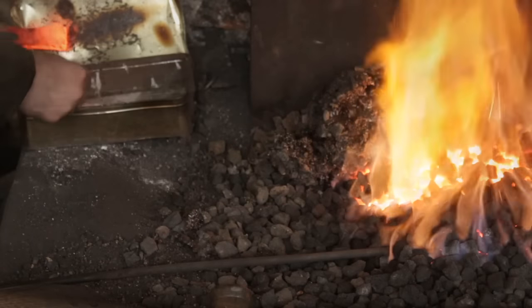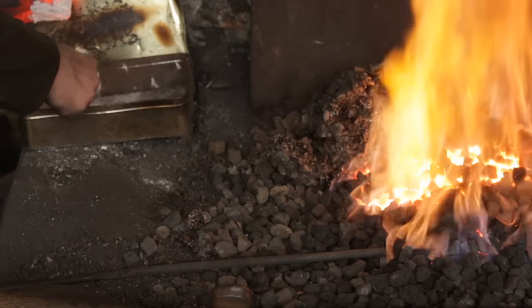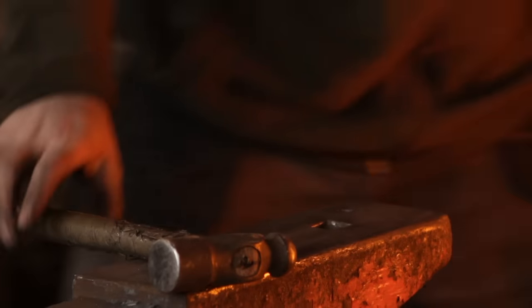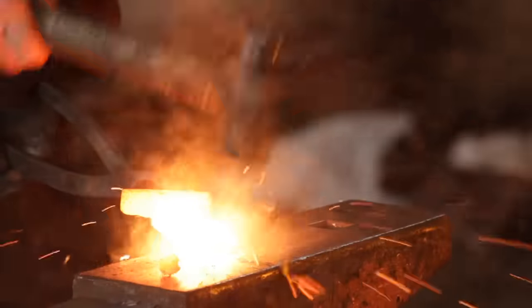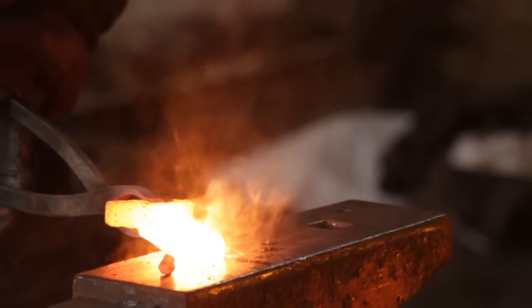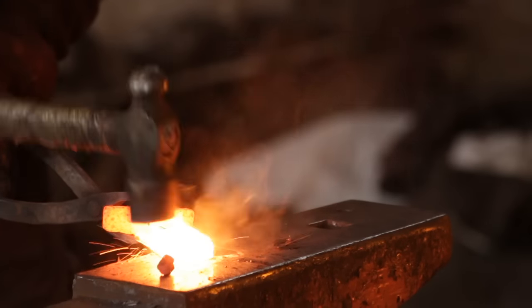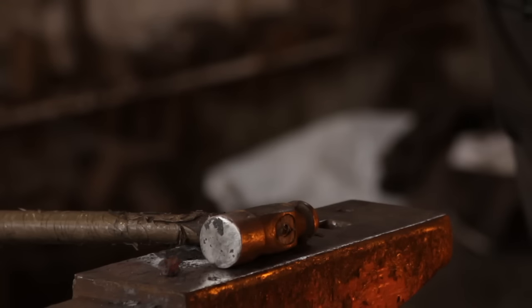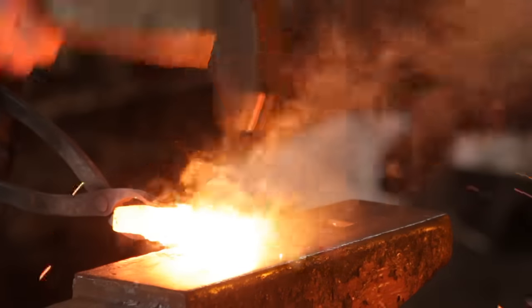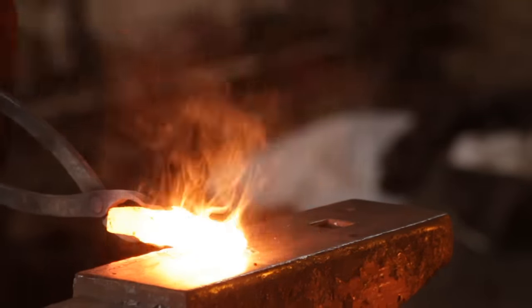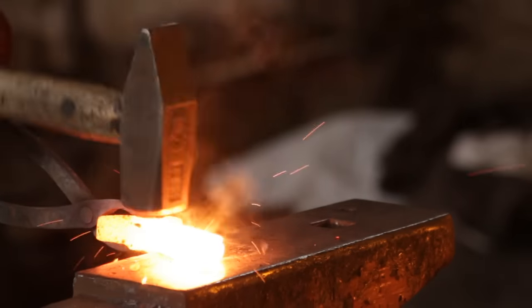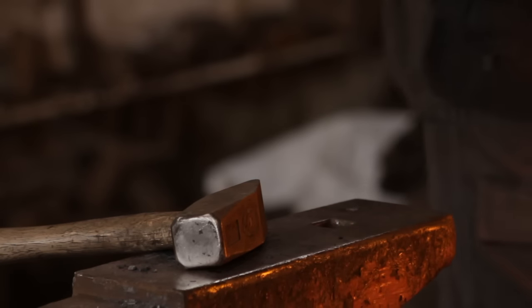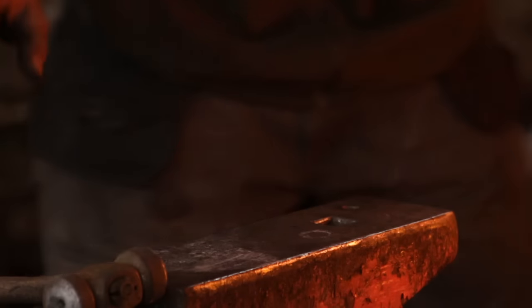So preheat it once the carbon steel is hotter, stick some more flux on it and weld. So I probably used five, six welding heats to get this to fix. And I actually welded by hand this time. Normally I'll do these under the power hammer because it's quicker, but I was in the mood to do it by hand so I did it by hand. Swapping between the wide faced hammer, well I started welding with the narrow faced hammer just to tack the carbon steel into place and then actually weld properly with the wide faced hammer.